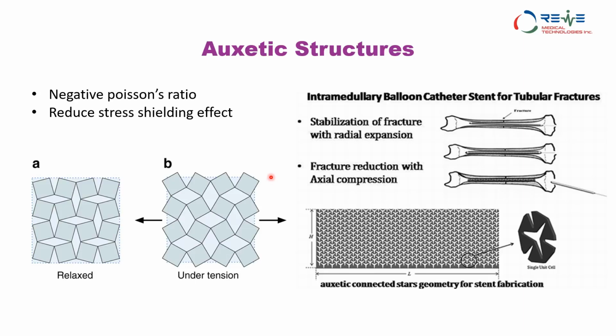This makes them unique, and they can be used for developing stents to avoid stent migration. They can also be used for bone implants to reduce the stress shielding effect, which is very common with bone implants. Our group developed an intramedullary balloon catheter stent for tubular fracture. The main concept is that the stent that we develop is implanted inside the bone in the intramedullary region by making a small incision on this side.